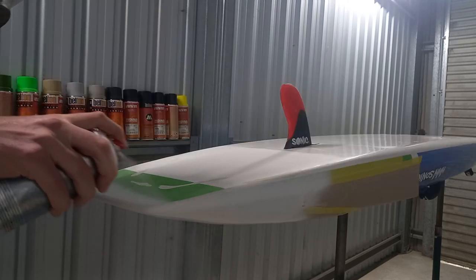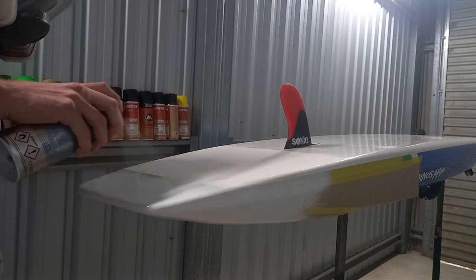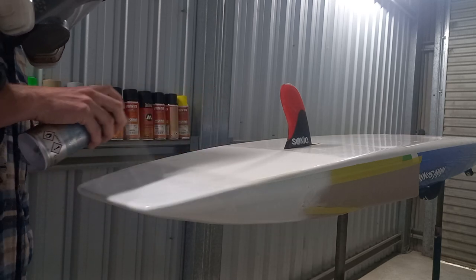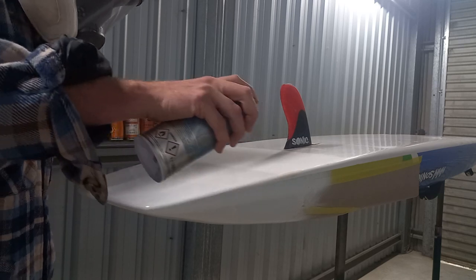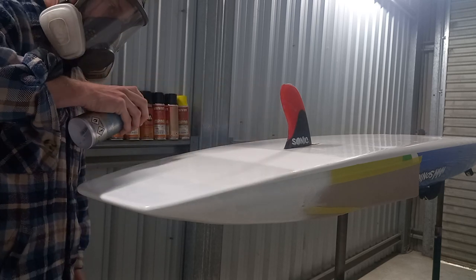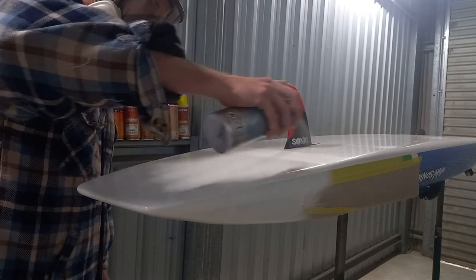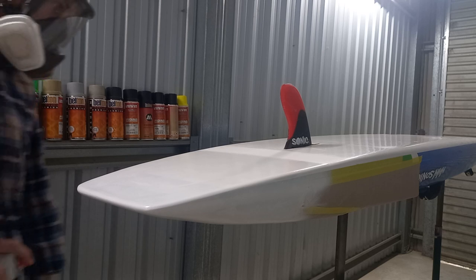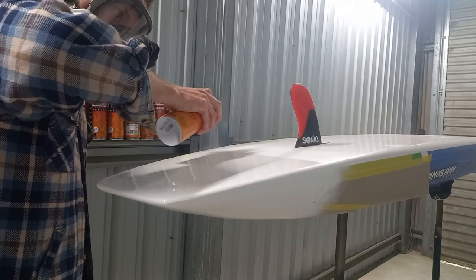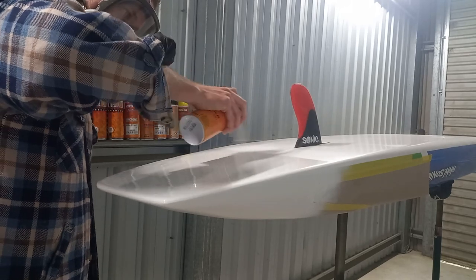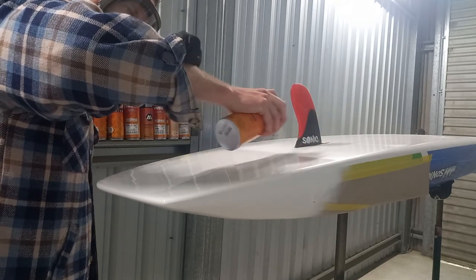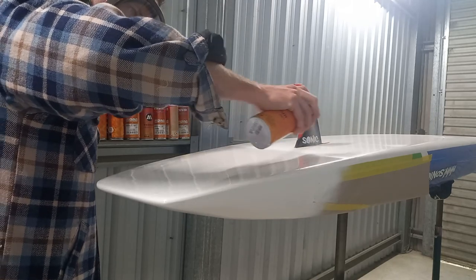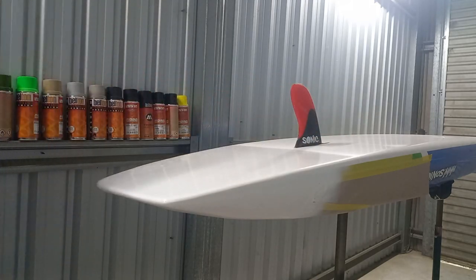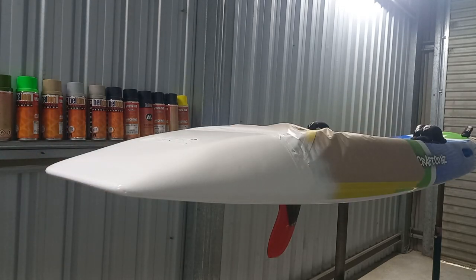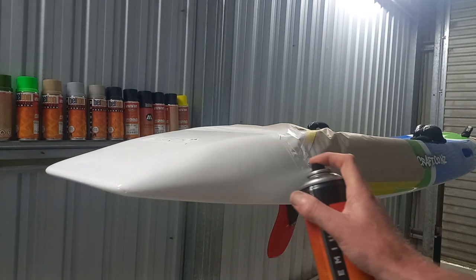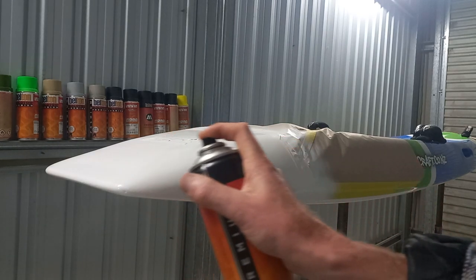The underside's a little bit different because I want my white paint to blend into the original white paint of the board. So I've sanded with 600 wet until the fin of the board. I want my clear coat to stop about a sharpie's length before the fin, and I want my white paint to stop about a sharpie's length short of where my clear coat would end. So this is the clear coat going down here. We want to make sure that all of our white paint that we've laid down is covered by clear, but we don't want to be going beyond where we've sanded onto original glossy paint. If you're putting paint on top of old paint that hasn't been sanded, that's where you're going to get peeling from and your paint job just won't last.